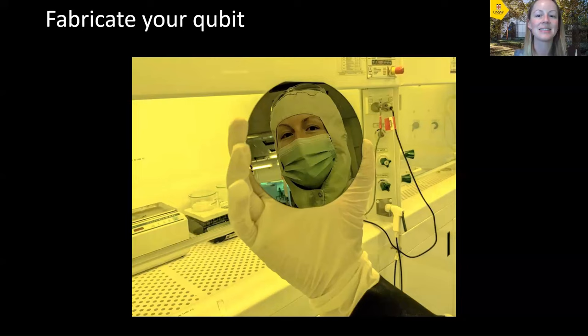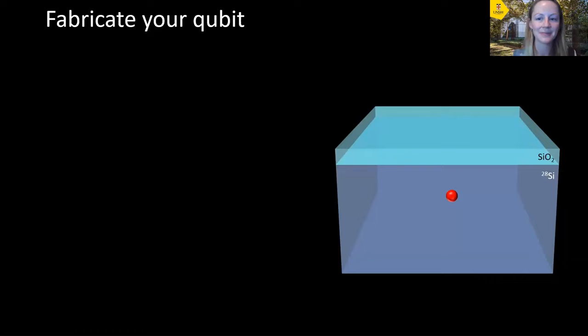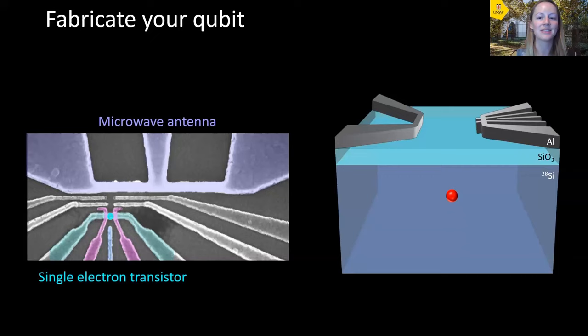And it's just fresh and ready to begin fabrication, where you would first of all grow your oxide on the surface, and then you implant a single donor atom into the silicon. This is done by firing a single atom using an ion implanter. Then after this, we have to fabricate our nanoscale electronics on the surface by patterning the aluminium gates using the electron beam lithography method that I mentioned earlier. And these will enable us to control and read out our spin qubits in future.